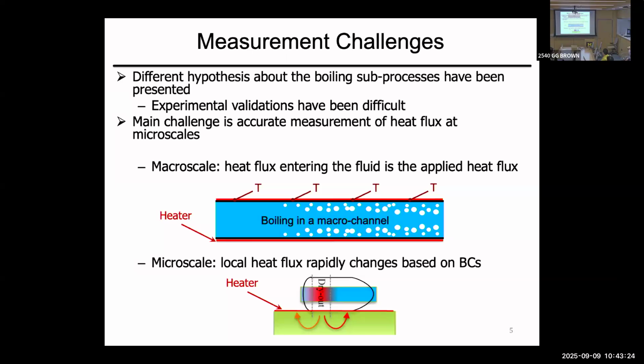So what's the difficulty? If you go back to the literature in large tubes, you apply a heater, you produce bubbles and you measure the surface temperature. And you are interested in developing an empirical correlation, right? So the heat flux that you apply to the surface, that you write down, is the same heat flux that ends up in the liquid, on average, right? And yeah, there might be some conduction along the wall, but if you design the experiment right, all the heat flux on average will end up in the liquid.